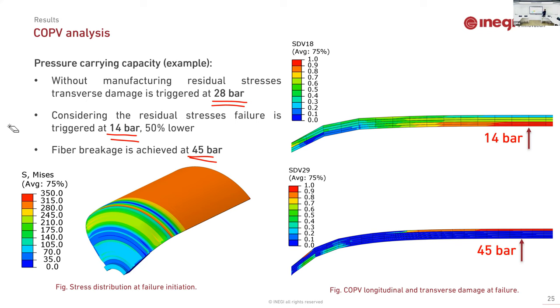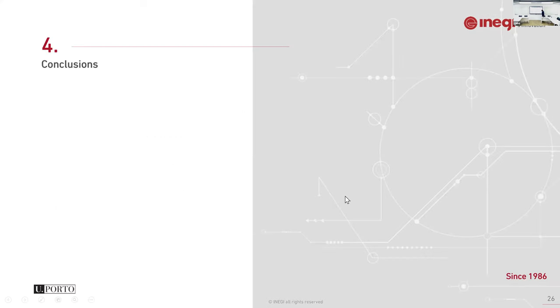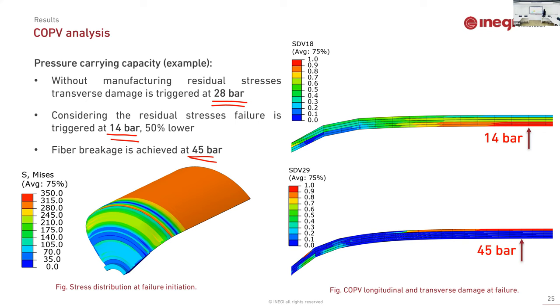And the constitutive model is implemented in a subroutine. That's why I can do this in a coupled or uncoupled way with a thermal solver, if I have a thermal simulation also. If I have the thermal part, I simulate the heat transfer, and you get the temperature profile, and maybe the temperature in the region is different. And so the curing evolution in all the geometry is slightly different.